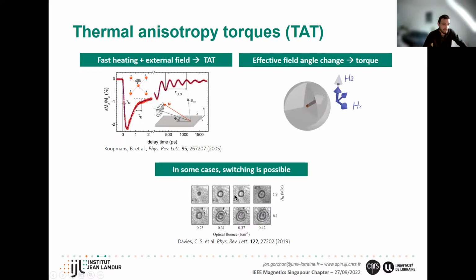And so they got this kind of bullseye rings pattern where, depending on the heating, so this is done with an optical pulse, so they have a Gaussian heating profile. Depending on how much they heat, they could precess more or less and switch or switch back, and they got this kind of pattern. And so this is actually also going on in our experiment because we're having a very fast heating. We have this strong in-plane field, and so we also have this kind of torque helping us to switch.